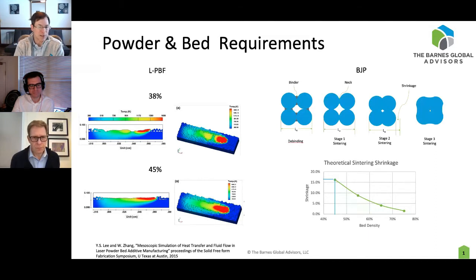And so, again, these are simulation results from a couple of years ago, but I thought it was really nice to illustrate. Compared to the right-hand side, if you have a 45% bed density in binder jet, you're going to end up with 17% shrinkage, which is a very large number to accommodate. If you're thinking about making a 14-inch ring at the end, you need a 17-inch ring at the beginning. And then lots of things happen in order to get that 17-inch ring shrinking down to a 14-inch ring. That comes with a whole host of other problems that we haven't even talked about yet.